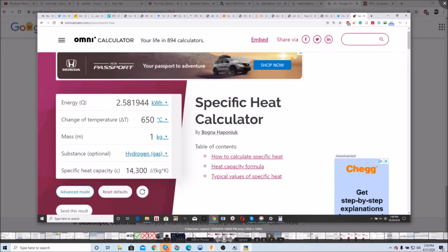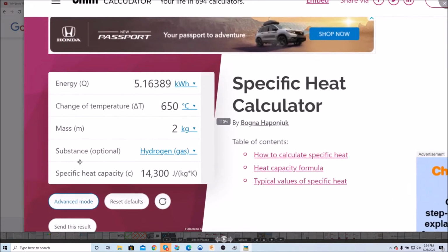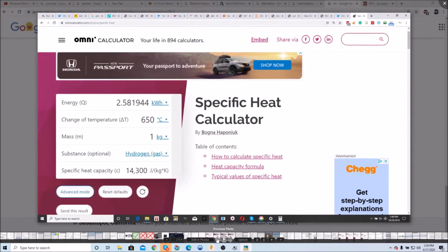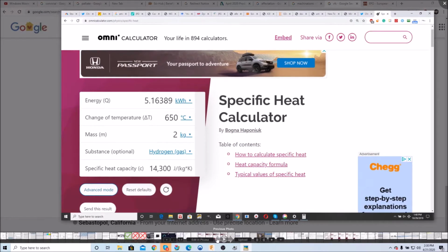So, some energy consumption estimates. We can calculate how much energy we need to crack our ammonia based on the total mass of metal that we're heating up. So that's going to be the catalyst channel. The rate of hydrogen and nitrogen flowing through, which has a heat capacity, which is going to absorb that heat that we're inputting into the reactor. And so we can calculate it comes to around 8 kilowatt hours per kilogram of hydrogen formed.